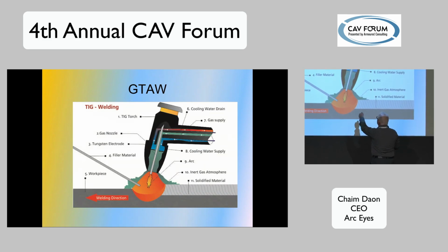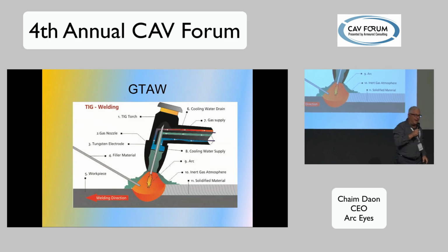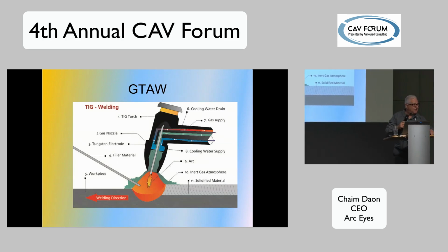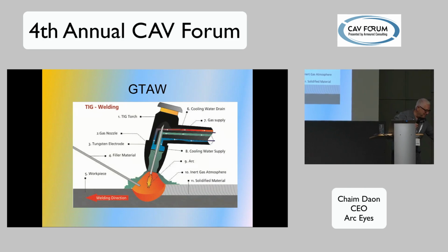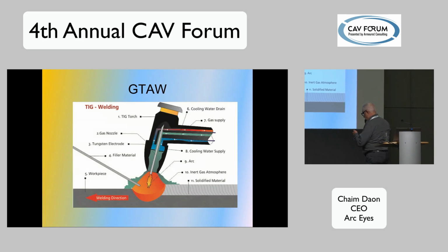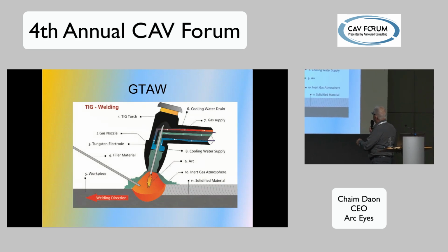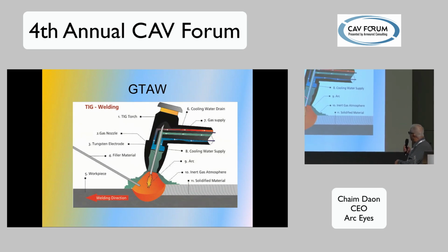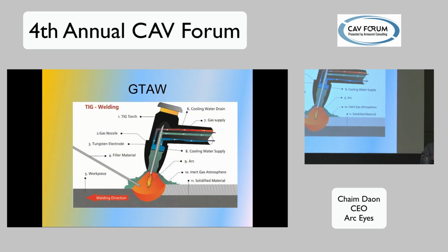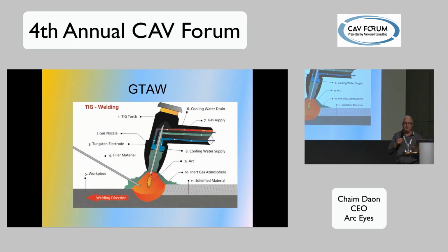The gray area is shielding gas. Usually it's argon, but it could also be a composition of argon with other gases such as helium, which protects the arc, because what we don't want is oxygen to get into the molten weld metal. We want to keep oxygen out.